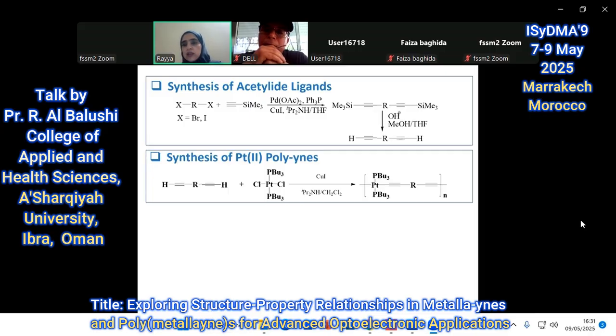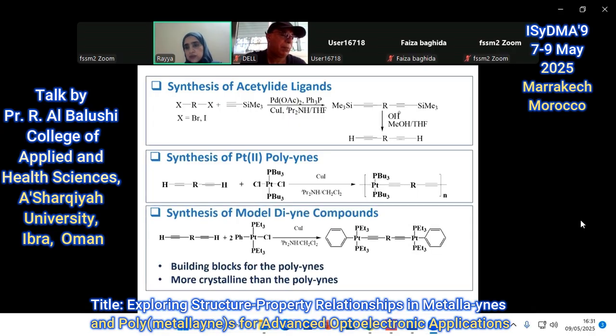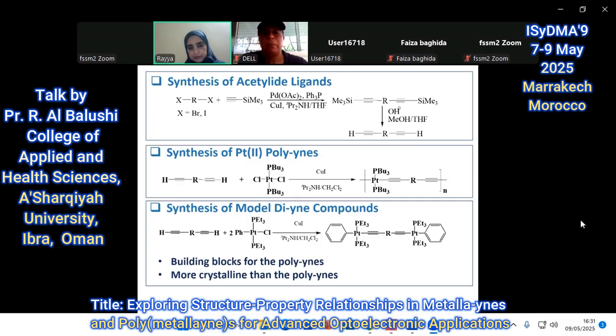As we know, polymers are big molecules, and we cannot, of course, characterize them fully, especially by X-ray crystallography. So people tend to synthesize a model compound, the di-yne compound. These are building blocks for the polymers, and they are more crystalline than the polymers. So once we have an X-ray of the di-yne, then we will be able to characterize it, and so we'll have clear information about the polymer morphology, like bond angles, bond lengths, and so on.